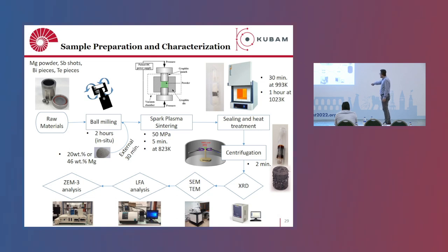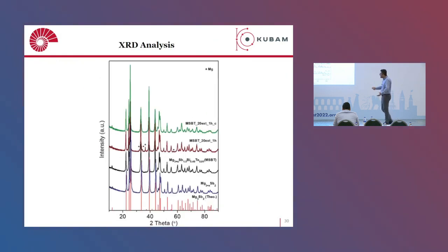Of course, the first thing we do is XRD for phase analysis, TEM and SEM for the microstructure analysis, LFA for thermal conductivity, and ZEM3 for the electronic transport characterization. So this is the XRD diagram. This is the theoretical pattern. You can see that this is magnesium 3 antimony 2 as it is.